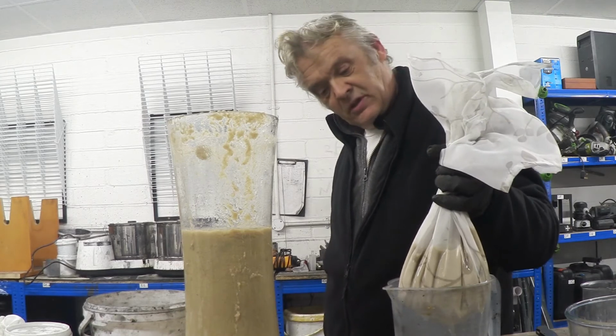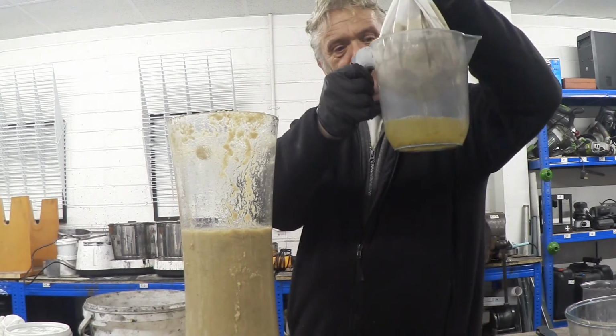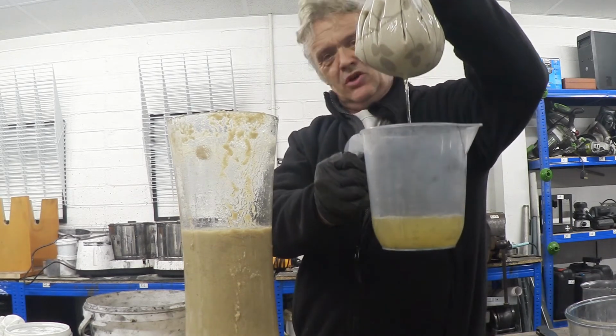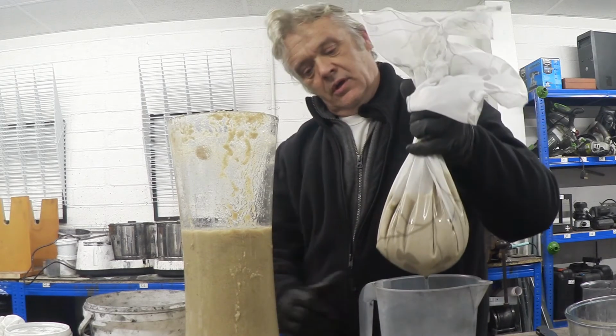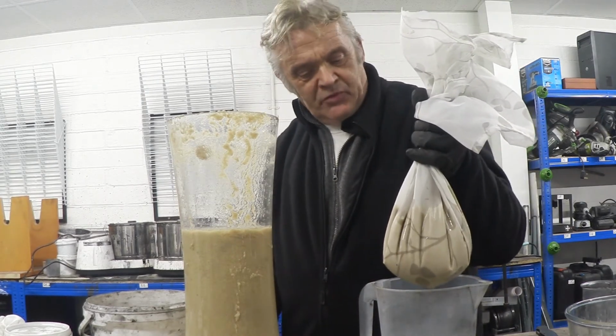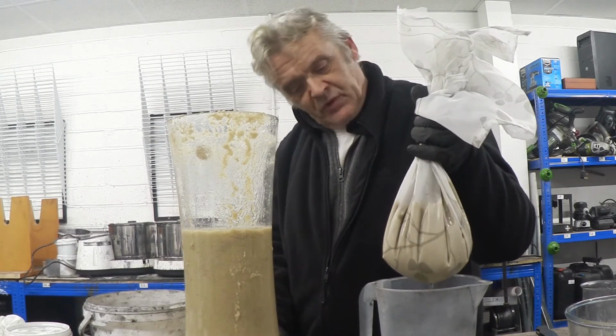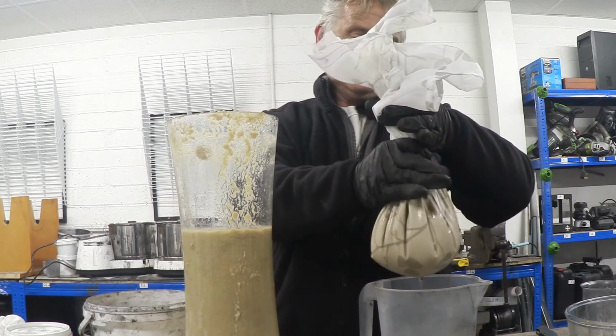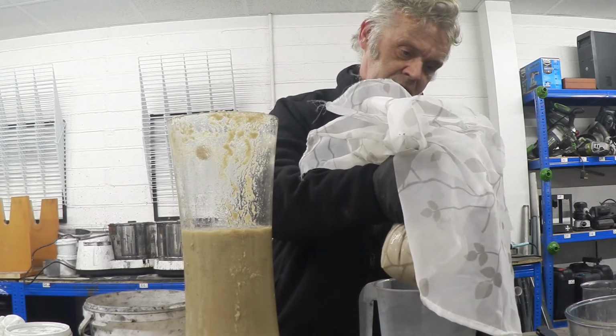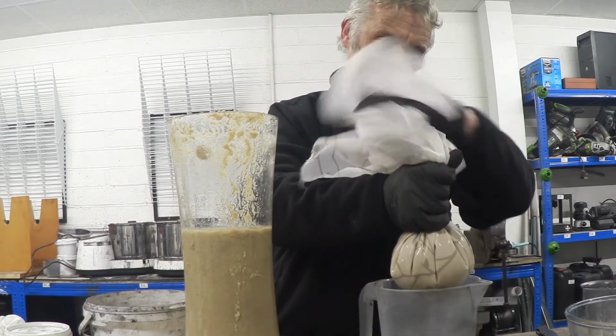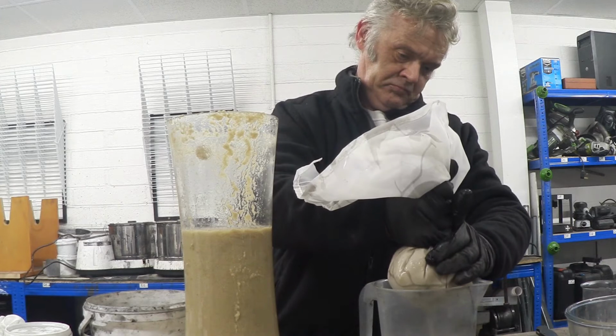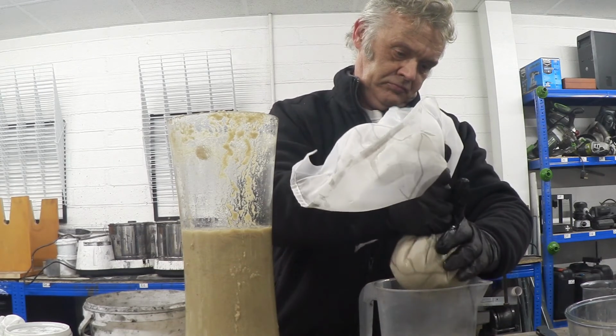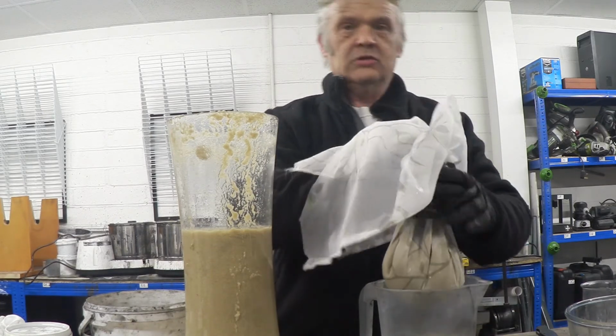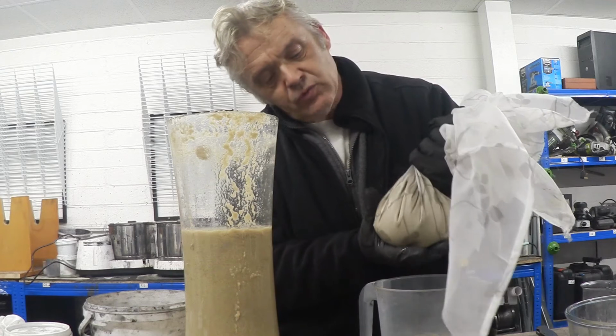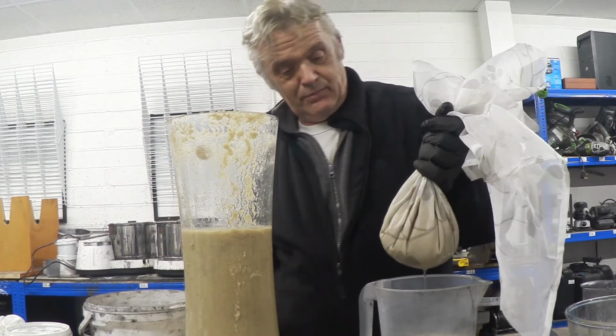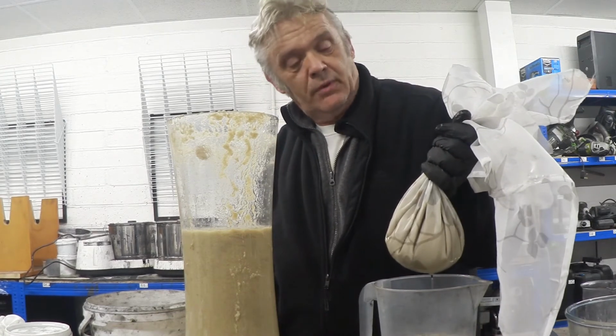And if we pick that out, you can see that we're getting a liquid there in the bottom as it all just drains out. There we go, a nice clear liquid draining out. Now there will be some fat and bits of wasted material in there, which is why it's kind of a yellow colour. The more brown it is, then the more tannin that you've lost. So having that yellow colour is telling me that it's losing fat, but quite a lot of the tannin has cross-linked in with the casein there. And all I'd then do is just leave that to drip, obviously.